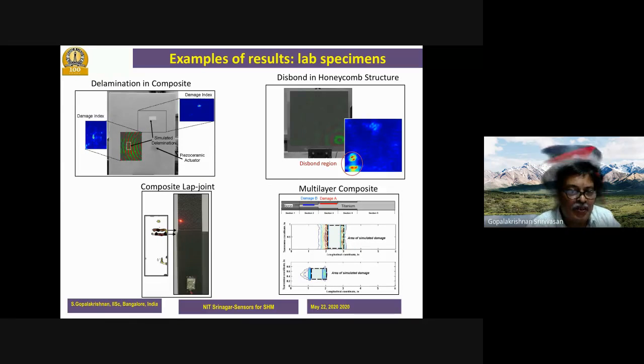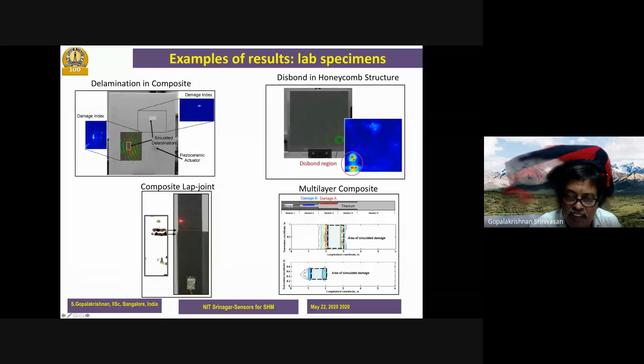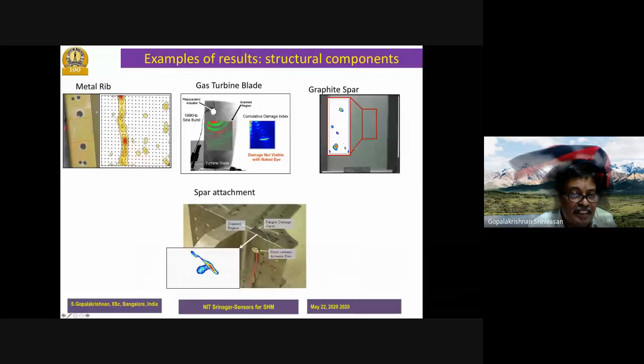And we have done this experiment on a very, very large number of samples, both in lab as well as in field. This is a honeycomb structure. This is a multi-layer composite. They are able to get the damage scenario. This is a composite lap joint. This is the metal rib of an aircraft. Where this region we had the damage, we could figure out exactly where in this region it was. This is our GTRE blade, damaged blade, where damage was 20 micron size.